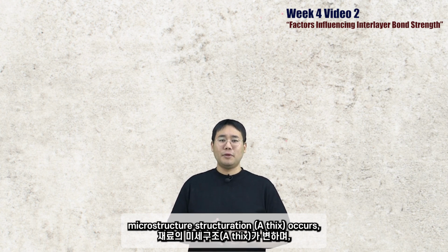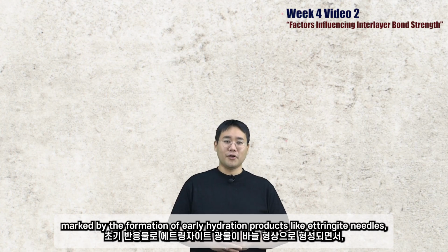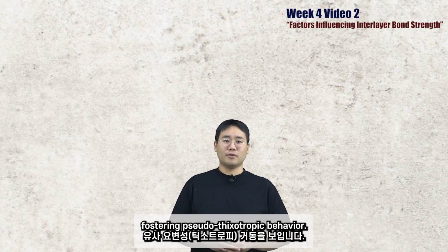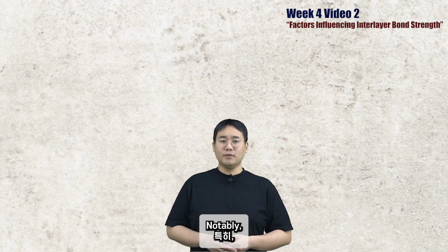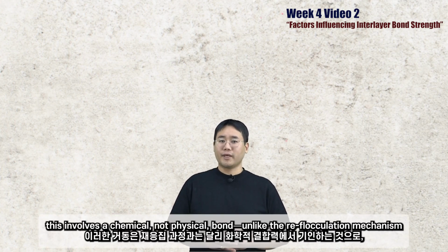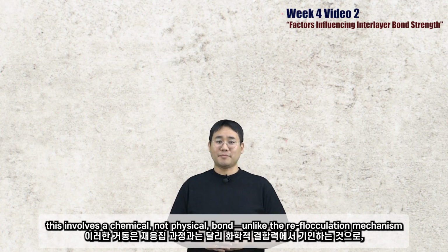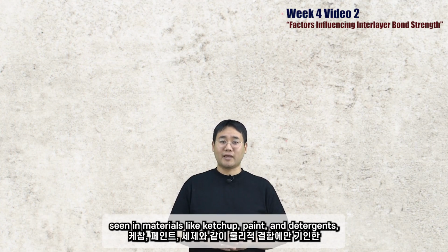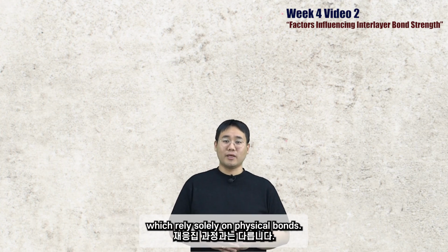Following reflocculation, microstructure structuration occurs, marked by the formation of early hydration products like ettringite needles, fostering pseudo-thixotropic behavior. Notably, this involves a chemical, not physical, bond, unlike the reflocculation mechanism seen in materials like ketchup, paint, and detergent, which rely solely on physical bonds.